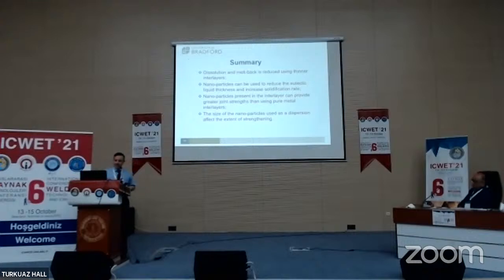So just in summary then, dissolution and meltback can be reduced by controlling the thickness of the interlayer. Second, the nanoparticles can be used to reduce the eutectic liquid thickness and thereby increase solidification. The nanoparticles present in the interlayer can provide a greater joint strength than if we use just a pure metal eutectic forming interlayer. And the size of these nanoparticles affects the dispersion process and the extent of strengthening that we see within the joint.